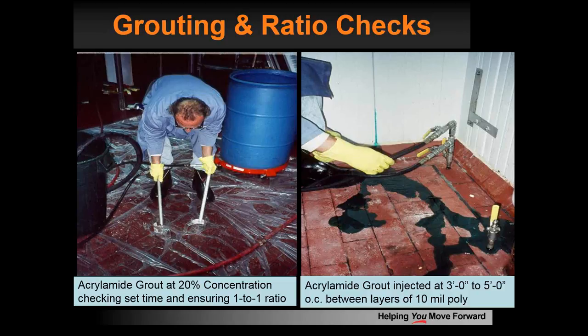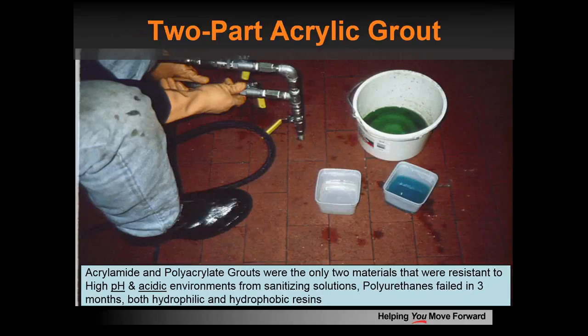We came up with a plan to use acrylamide grout, which is very resistant to acids and chemicals, and we went with a 20% solution, which is about twice the normal concentration for acrylamide. And on the picture on the right, you can see we're starting to grout through the floor. We actually core drilled through the floor at about a 3 to 5 foot spacing, and we put an acrylamide grout in between the two layers of 10 mil poly to actually make the insulation layer a monolithic membrane.